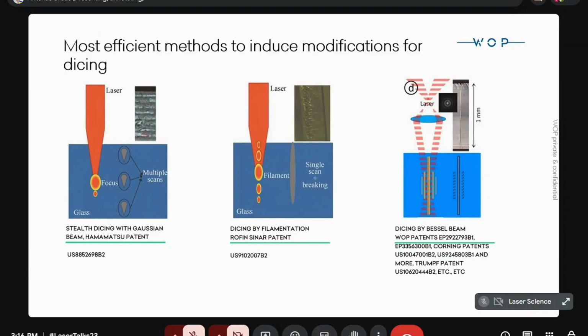What are the most popular and most efficient methods to induce modifications for dicing? Quite an old method is stealth dicing. That is how Hamamatsu calls it, and it is used by the Disco company. So you introduce damage inside of the glass. If it is a thick workpiece, you place multiple scans, and then you simply break along this line. You can do it in one go in quite big thickness.